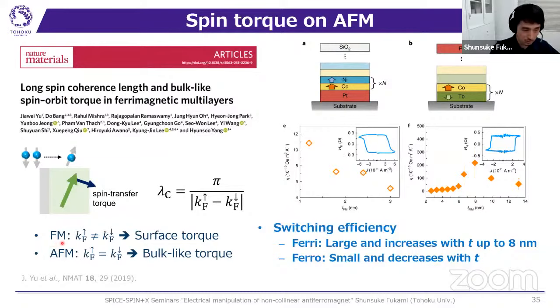So for the ferromagnet, because the wavelength for up spin and down spin is different, the spin torque is basically active only near the surface. But for the antiferromagnet, it should be active over a long range. So the spin torque for the antiferromagnet is like a bulk-like torque, which is different from the ferromagnet.